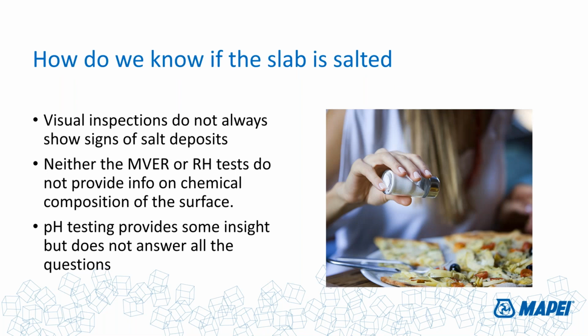So how do we know if a slab is salted? It's really not something you can see visually, and it's not something you're going to find out by doing moisture vapor emission rate or RH tests. The pH test will provide some insight. Again, keep in mind that the pH test only measures remaining hydroxyl, which is the calcium hydroxide portion of it, but doesn't give you any idea of what concentrations there might be of sulfate ions, chloride ions, sodium ions, or calcium ions, the other kinds of things that are going to be hygroscopic and absorb moisture over time and create these kinds of problems for you.